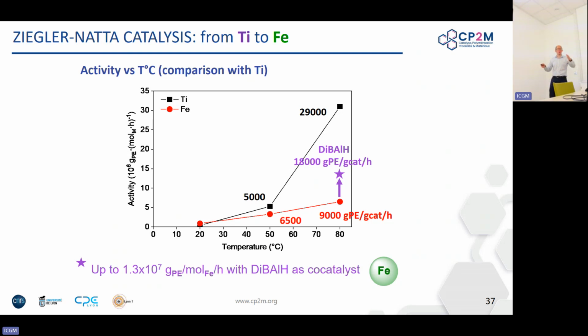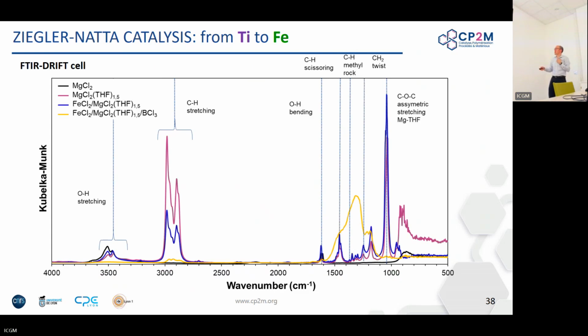Instead of treating a magnesium dichloride support with TiCl4, you will treat it with iron chlorides. And you end up with a catalyst that can be very active and almost as active as some very good titanium catalysts. So this is a reference catalyst we have in our lab, and you can reach values that are comparable to and better than chromium or Phillips catalysts, for instance.